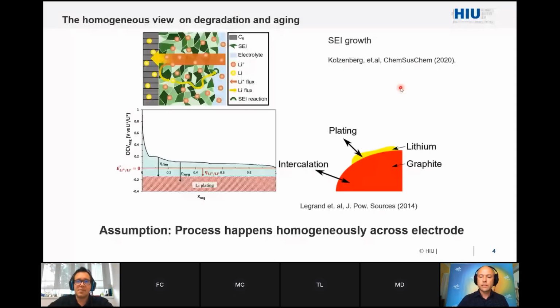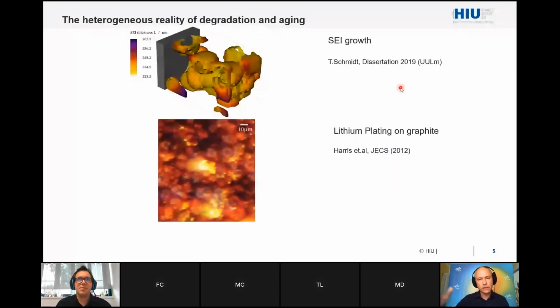You say these are changed by this degradation phenomena. But the reality is unfortunately different in electrodes, and you have seen examples in the first talk that the production process is of course not perfect. It's nearly perfect, we know that, but it's not really perfect, and there are inhomogeneities due to the process of production. Then during operation, you create inhomogeneities in the electrode, and therefore, for example, for the SEI growth, you find that the SEI is not growing homogeneously all over the electrode.